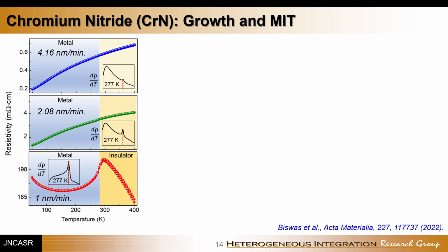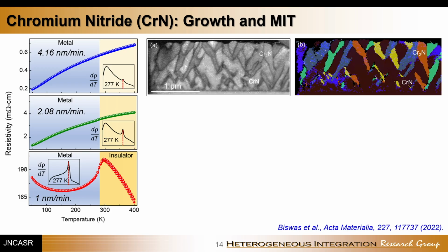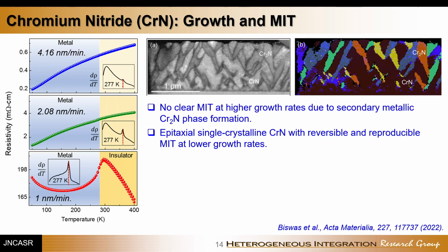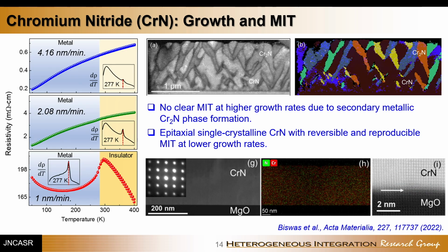VO2 has many different phases. Unless you hit the M1 VO2 phase, you will never get a 3 to 4 orders of magnitude transition. Similarly, in this particular case, unless you reach a stoichiometry of 1:1, you will never get a metal insulator transition. So this is what is shown there. When you grow them at a high growth rate, because of the formation of secondary Cr2N grains, they don't show any transition. It's only when you reduce the growth rate to a much lower rate of 1 nanometer per minute, you see the crystal looks perfectly epitaxial, single crystalline, and they almost invariably, or reproducibly, show this metal insulator transition.